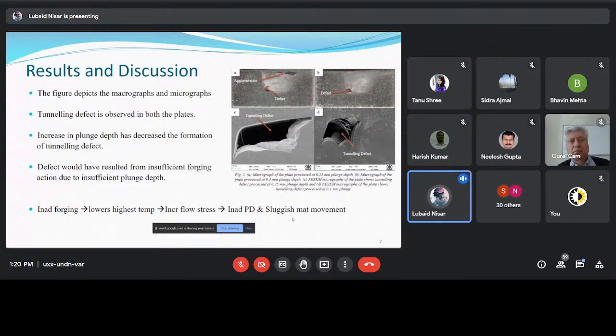Then using FESEM, we got the micrographs, and we can clearly see that in case when the plunge depth was 0.2 millimeter, the tunnel was more prominent than in case of the time we used 0.3 millimeter plunge depth. Thus, we can clearly say that increase in plunge depth has decreased the formation of tunneling defect. This defect is actually resulted from insufficient forging action due to insufficient plunge depth.